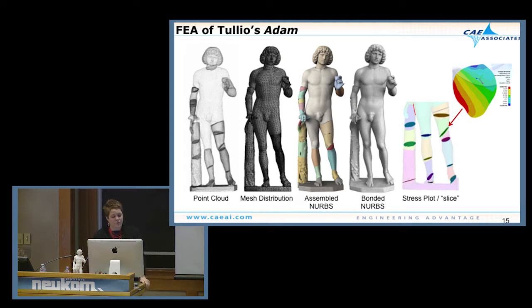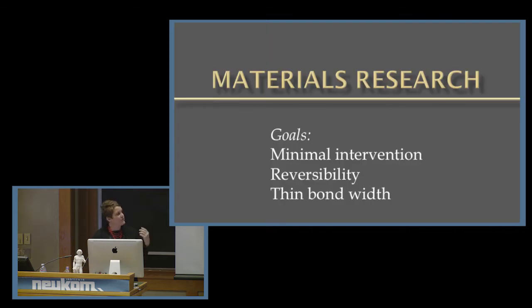And one of the things that we found at the end of this finite element analysis was that there was not one place on the sculpture where the load on each joint exceeded 100 pounds per square inch. So you think of this very large sculpture, 6 foot tall, 780 pounds, and the forces on the joints were actually quite small. Surprisingly small, at least that's what we thought was surprising. And that was really important to our research in adhesives, because then we could narrow in on finding just the right type of adhesive, one that wasn't overly strong or too weak. So the goal of our materials research, the next phase after the finite element analysis, was that we felt like we better understood the structure of the sculpture.